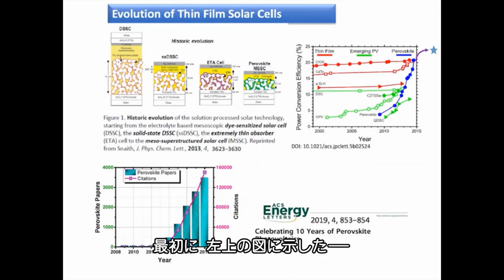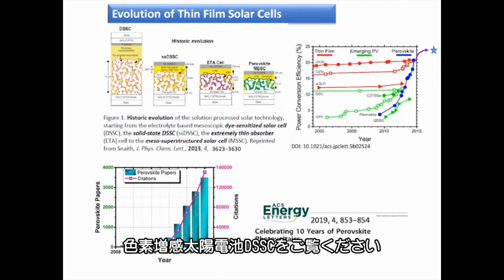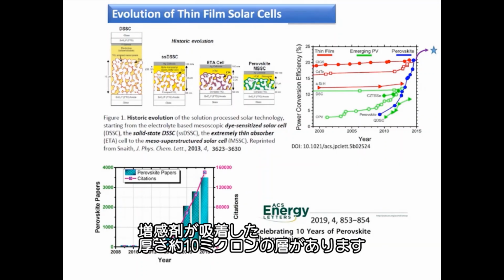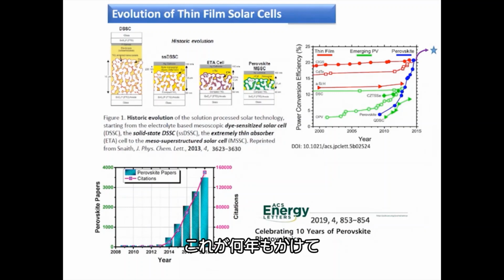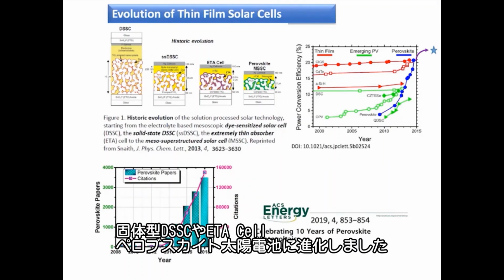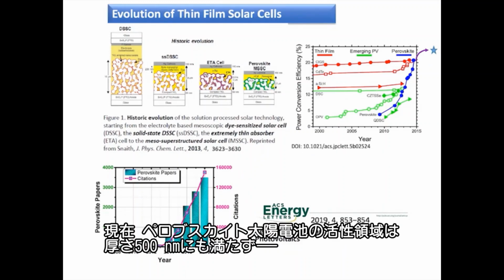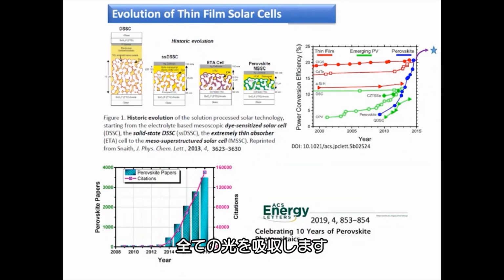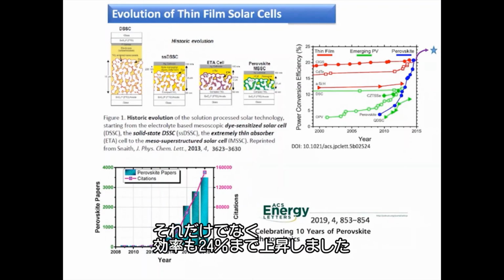The first one you can see here, dye-sensitized solar cell, or DSSC, on the top left corner, where we had about a 10 micron thick film on which sensitizers were absorbed, and this has evolved over the years into solid state DSSC, extremely thin absorber cell, and perovskite solar cells. Now the perovskite solar cells use less than 500 nanometer thick active area, and that absorbs all the light. And more than that, the efficiency has gone all the way up to 24% in this case.